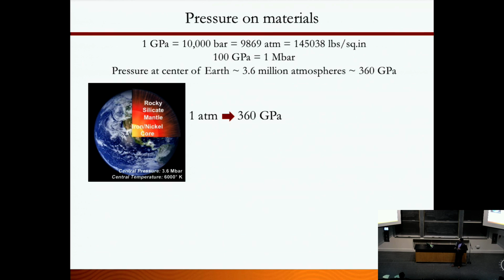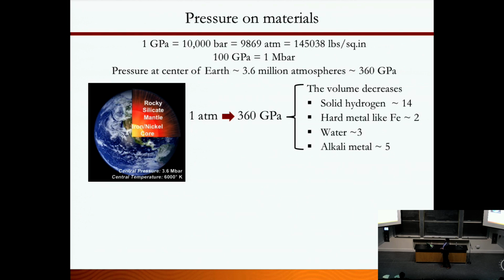How do you conceive this kind of thing when you apply really high pressure to a material? One thing you can easily see happening is volume decrease. If I give you some examples, solid hydrogen, the volume decrease is a factor of 14 if you go from 1 atm to 360 GPa. A hard metal like iron, a factor of 2, water, a factor of 3, and an alkali metal, like a factor of 5. So the volume is really compressing. You're compressing the empty space in a material.